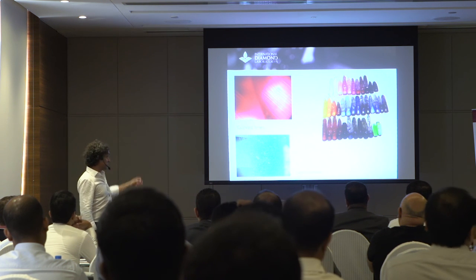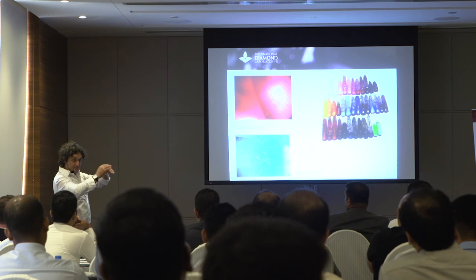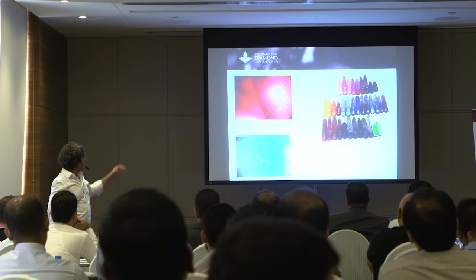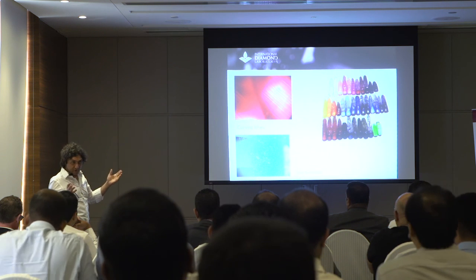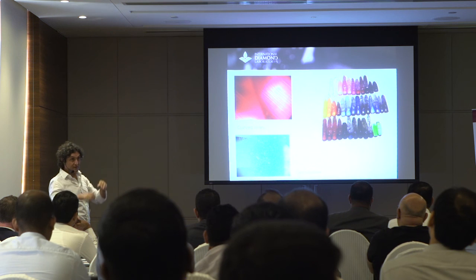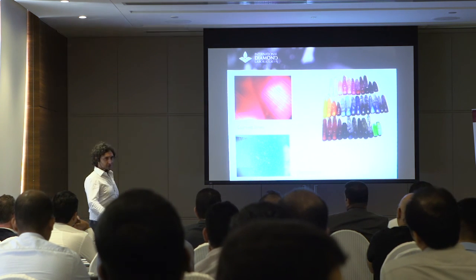Identification, we can see gas bubbles, the curved lines, because it will grow in layers. Curved lines will never be a natural stone. In nature, they have angles, they are not curved. So this is a quite easy synthetic to identify.